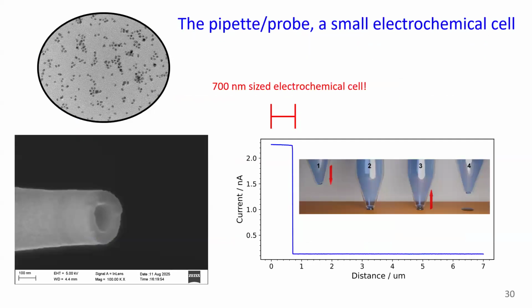To give you some perspective of the resolution and the size of the experiment, this is an SEM image of the probe, and you can see the size of the electrochemical cell is on the order of a few hundred nanometers. This is what's called a pull-up curve. After the pipette has approached the surface, as we retract the pipette, you can see the current drop once the meniscus no longer contacts the surface, and from there you can estimate the size of the electrochemical cell. To put it into perspective, if this is our substrate electrode with our catalyst deposit on it, we're measuring maybe a couple hundred particles at a time.